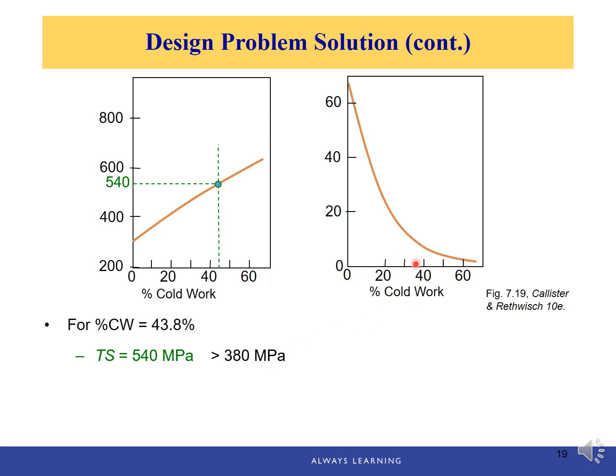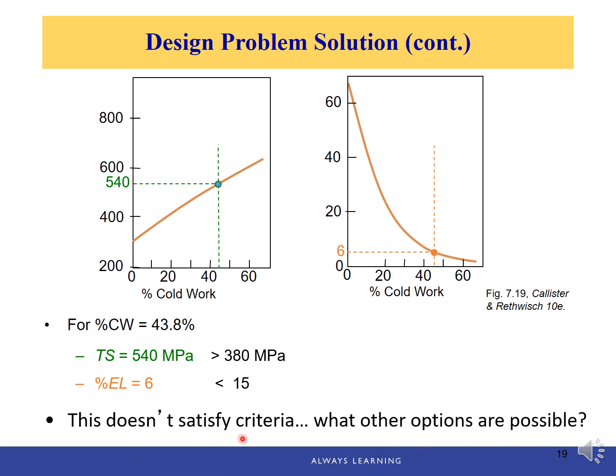Now let's check the ductility. Again, with 43.8% of cold work, we read the percentage of elongation, which is only 6%, but the required ductility is 15% of elongation, which means that because of the high strength after this amount of cold work, the ductility is greatly decreased. It doesn't meet the ductility requirement. So what other options are possible?